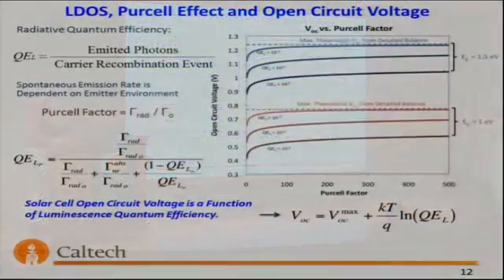And the spontaneous emission is important because if we're not working with semiconductors for which this quantum efficiency is high, then it's well known that a low quantum efficiency emitter in proximity or in an environment with an enhanced local density of states can have a higher radiative rate, and its effective quantum efficiency can go up because the local density of states affects the radiative rate and not the non-radiative rate. So this is well known from LEDs and fluorescence in biological systems, and people working in plasmonics know this very well. But this also confers potentially a benefit for low quantum efficiency semiconductors, low internal fluorescence yield, meaning low radiative to non-radiative rate ratios, and could potentially add some number of kT to the open circuit voltage of a solar cell. So that's something that has largely been unexploited to date.